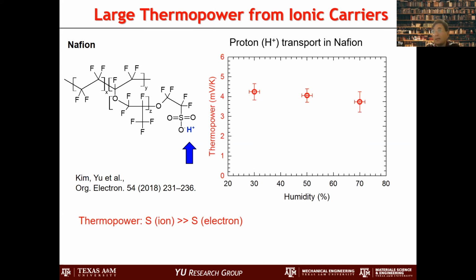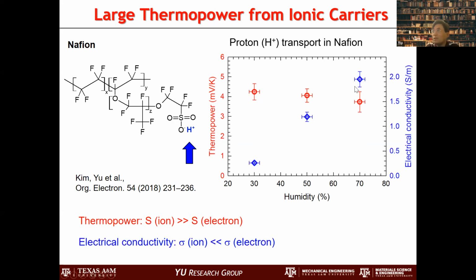But on the other hand, electrical conductivity is not that large. This is 2 Siemens per meter, which is many orders of magnitude lower than the typical thermoelectric material. So there is no material that always has better properties, right? So you have to pay the price. It's like our life: if you have something good, you have to give up something. So that's the problem. And then how do we utilize this and overcome this drawback?